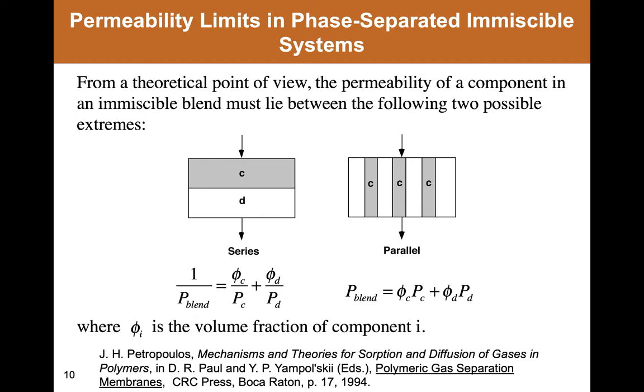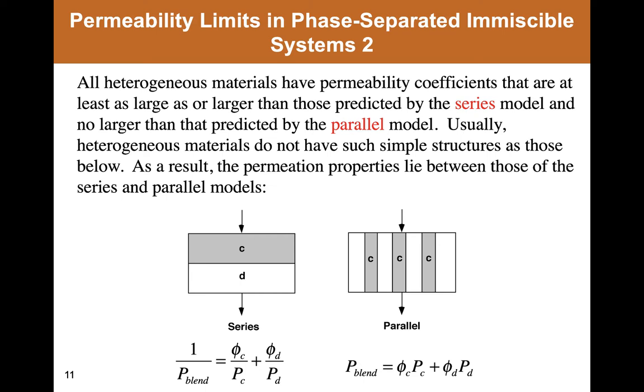And so, as indicated in the last slide, all heterogeneous materials will have permeabilities that are at least as large as the ones predicted by the series model, and no larger than that predicted by the parallel model. And typically, if heterogeneous materials don't have such simple structures, their permeation properties will lie in between the results predicted by these two models.